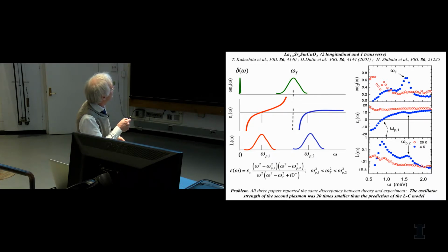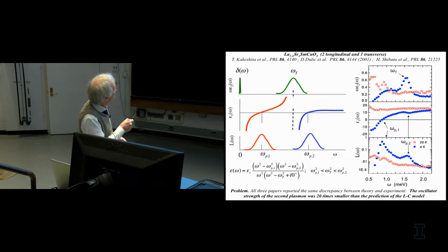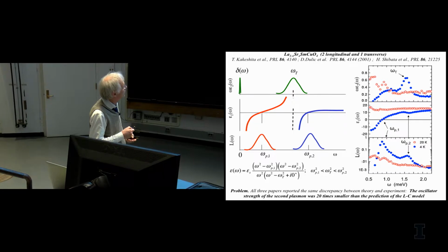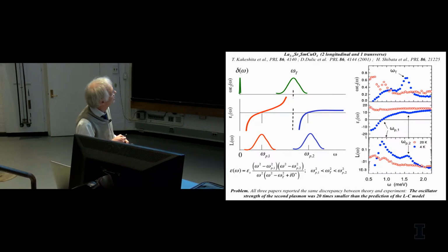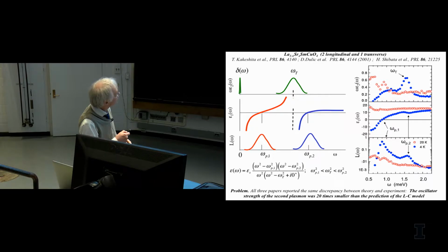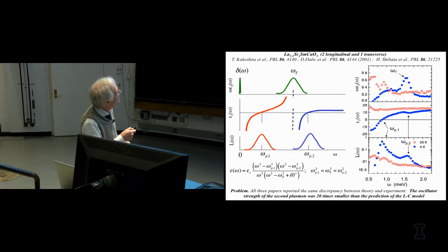If you plot it, rather than having only a delta function at zero frequency in the epsilon 2, in the imaginary, dissipative part, there's an additional peak. It's also called the transverse optical plasmon, that's what we called it. And there are two zero crossings of epsilon, corresponding to two plasma resonances which are longitudinal. All of these excitations are along the c-axis. It's just how they are oriented with respect to the propagation direction, which we take actually to be in the infinite wavelength limit here. So at the same time, several groups started thinking about it. Here are three papers in PRL, in the same journal.